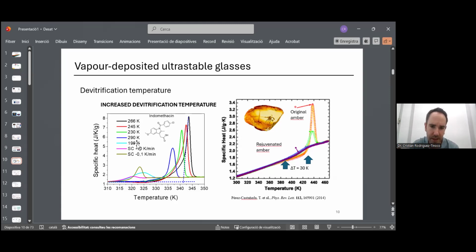Okay, but again, as I was saying before, as we change the deposition temperature, in particular, if the deposition temperature is 196 Kelvin, which is very low, then we have again this devitrification peak at a temperature similar to those that we get when we prepare the glass by cooling from the liquid. So again, if the temperature of the substrate is too low, then we again have a very unstable glass. We need the temperature of the substrate to have a proper value in order to be able to get a very stable glass.